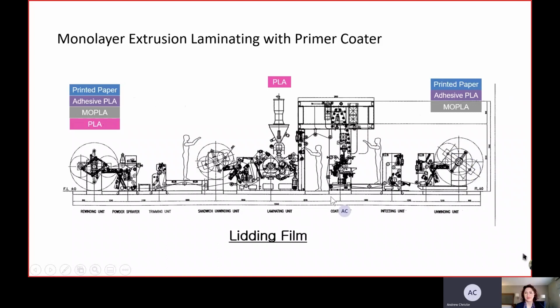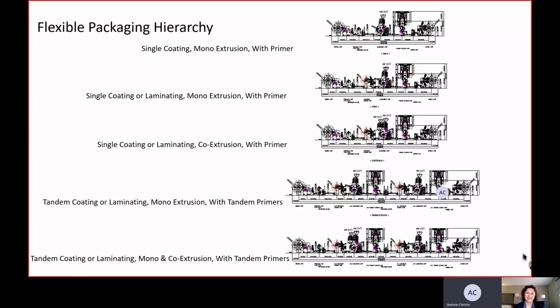We're going to unwind that substrate. We can again pre-treat that substrate, and then we can coat it with PLA for a sealant layer, or we can use that PLA to laminate a biodegradable sealant film onto this, which will then wind up creating a simple lidding type film for full biodegradability, because all of the components can biodegrade into the food for these microorganisms.